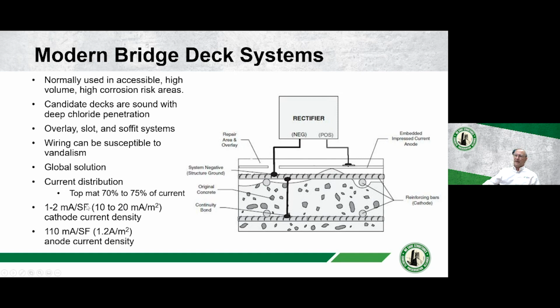Typically, your cathodic protection is run with 1 to 2 milliamps per square foot. That's your design current density, your cathode current density, which is equivalent to 10 or 20 milliamps per square meter. And the anode current density is 110 milliamps per square foot, and beyond that, the concrete will acidify. So you want to keep your current density down on the anode. So we have to check the current density on the reinforcing steel and on the anode.